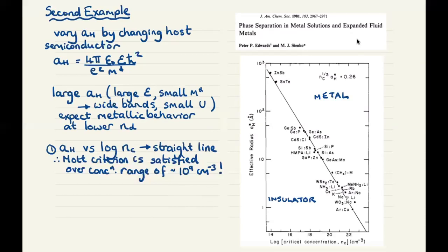Okay, and then let's have a look at some specific trends. If we first take a look at indium antimonide and tin telluride, these are extremely covalent semiconductors. They have a very small band gap, very large dielectric constant, and a very large hydrogenic radius, and we see that they become metallic already at very low doping. Again, as we'd expect from the Mott criterion.